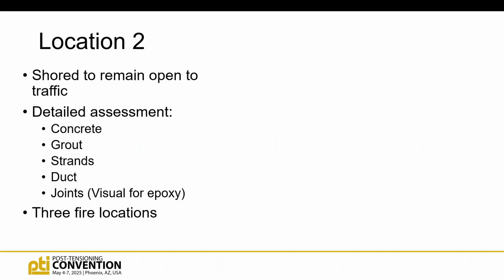So this one was shored to remain open during traffic. They kept it open during the whole process of our assessment. So we designed the shoring that you'll see here in a little bit. And then our assessment, we're looking at now at the concrete, we're looking at the grout, we're looking at the strands, the duct, the joints, everything, the epoxy segment joints, not the expansion joints.